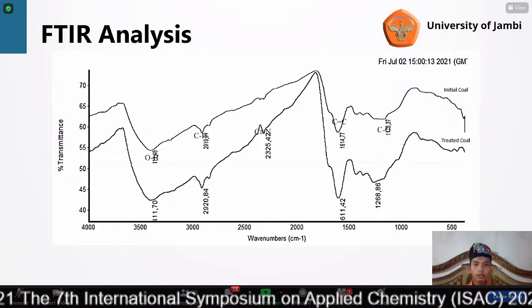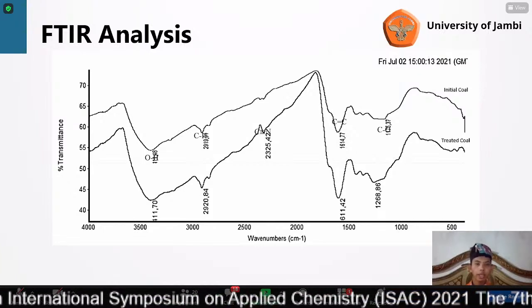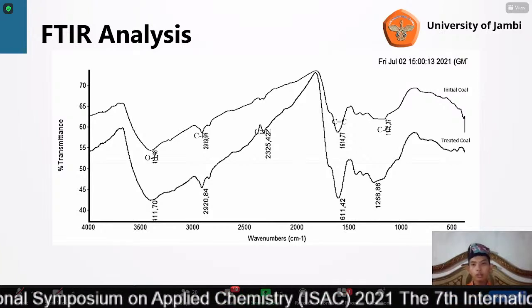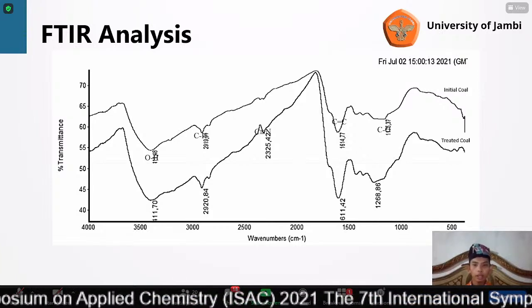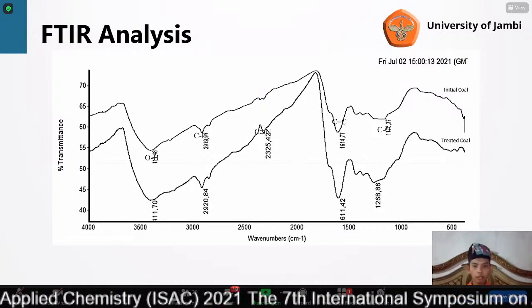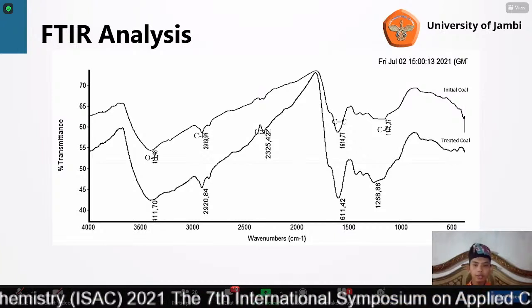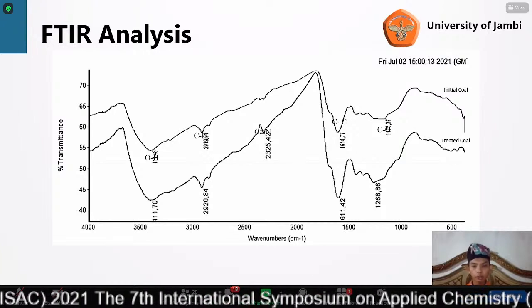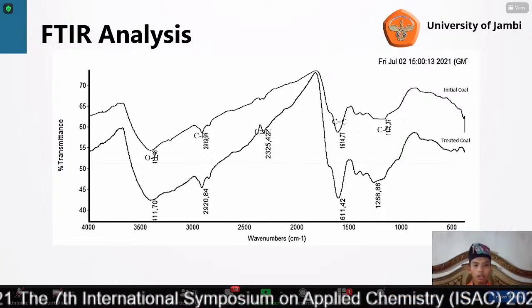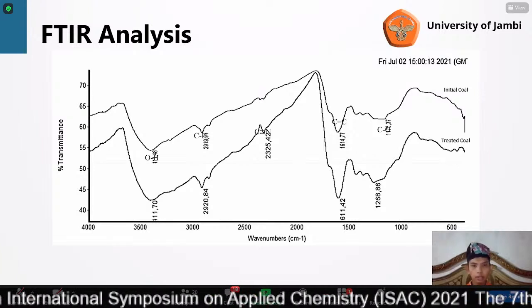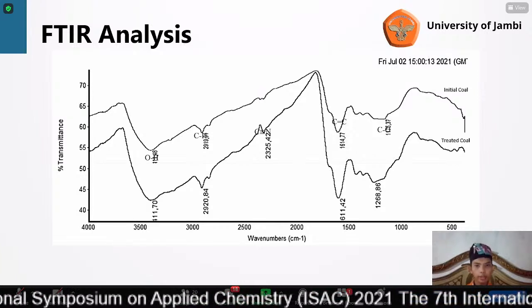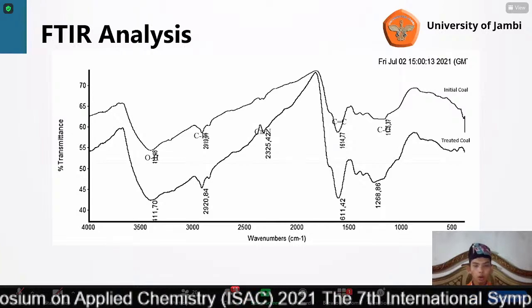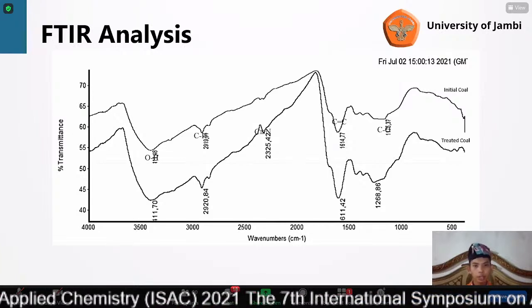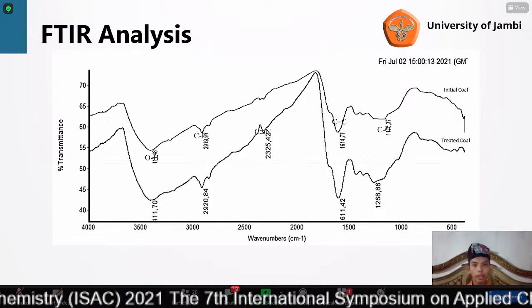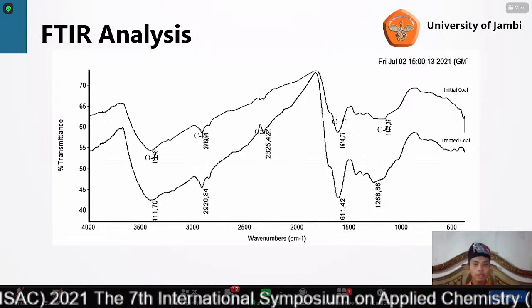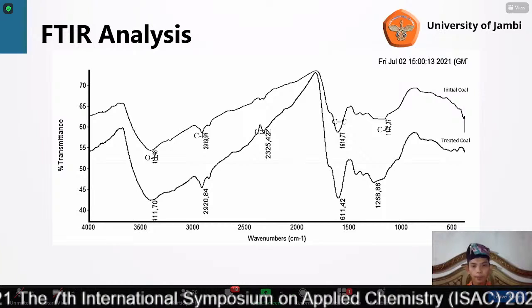And from FTIR analysis, we can see a change in the functional groups: four functional groups were found on the initial coal and five functional groups on the treated coal, adding one functional group on the treated coal. On the initial coal were found OH, CH, CC, and CO, and CN was added on the treated coal.